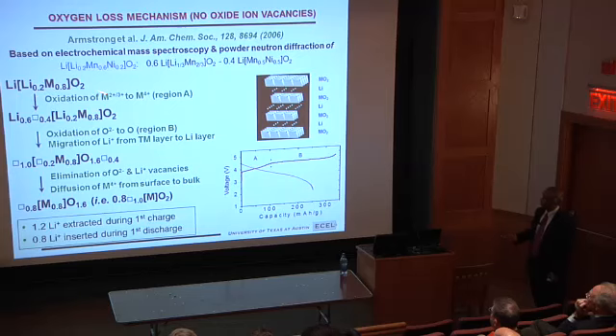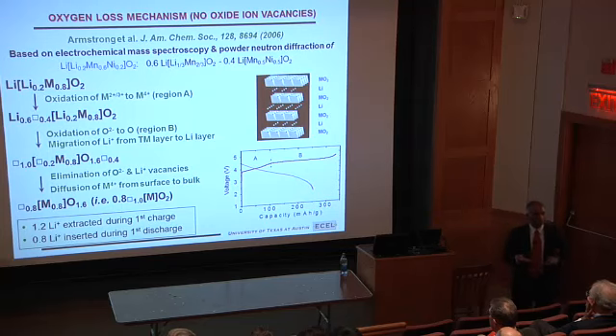That's because when oxygen is evolved, there are a lot of oxygen vacancies. So when you surface coat, you tend to keep the material towards this rather than towards this rearrangement. We can do a little calculation. We find when we surface modify, we tend to keep more this way. So this difference is decreased. So just by chemical conditioning of the surface, you are able to overcome some other problem.